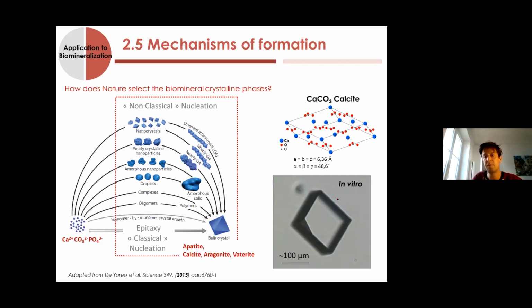For instance, in the case of calcite, you see that the morphology of the crystal in the end is directly related to the unit cell. So here you have a classical nucleation mechanism.